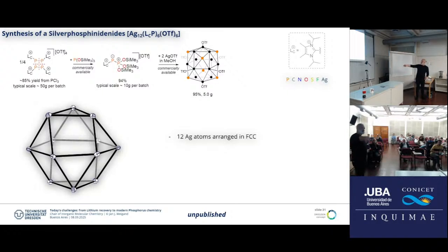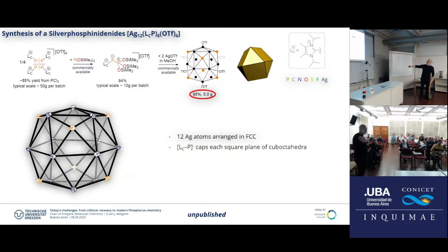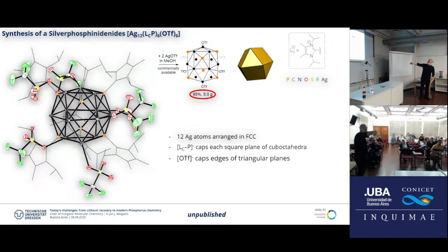We have 12 atoms in an FCC arrangement, and then, this is a cuboctahedron, and then on the square plane of the silver on top is one of the phosphorus, and the phosphorus carries, of course, the imidazolium ones here. And so, 6 of the corresponding silver atoms are coordinatively saturated by the triflate. You see the triflate, and that gives you a cationic silver cluster of the overall formula silver 12.